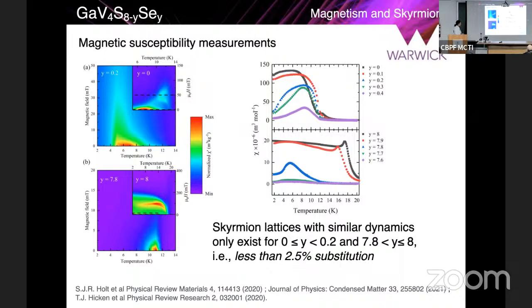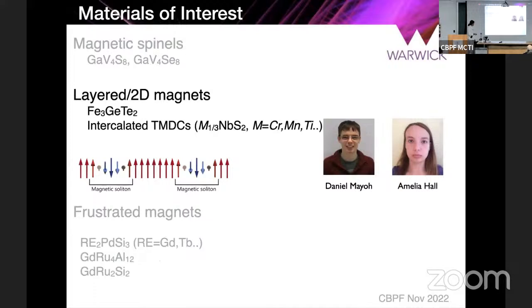So we conclude that if you substitute larger than 2.5% of the substituent, you just kill the phase transition that takes place, and therefore kill the skyrmion phase in these materials. So this was just to show how structure is very strongly linked to the magnetic properties in these materials.